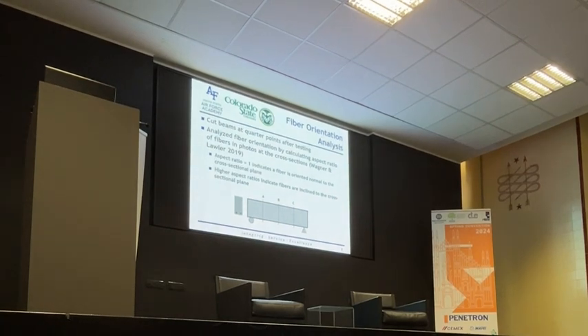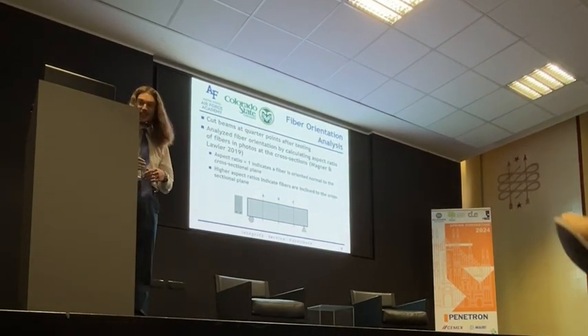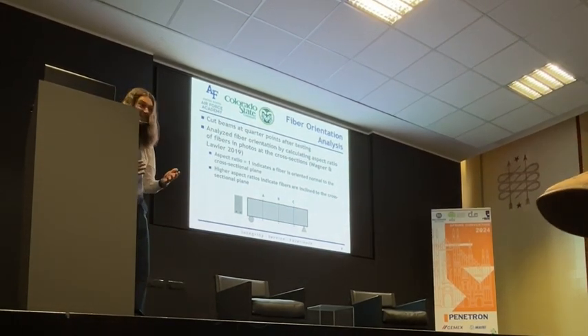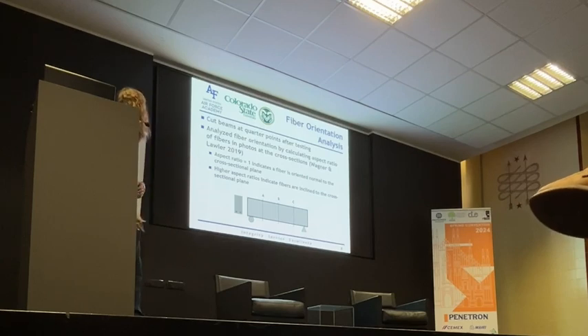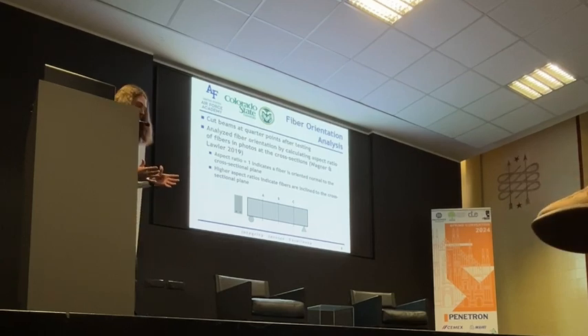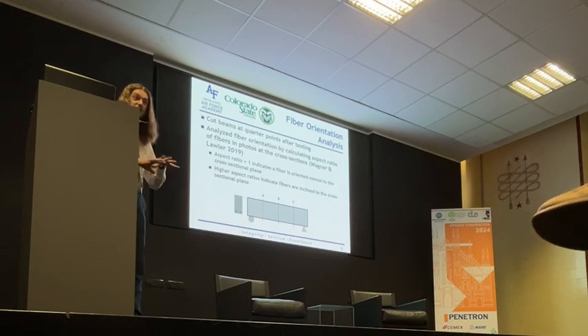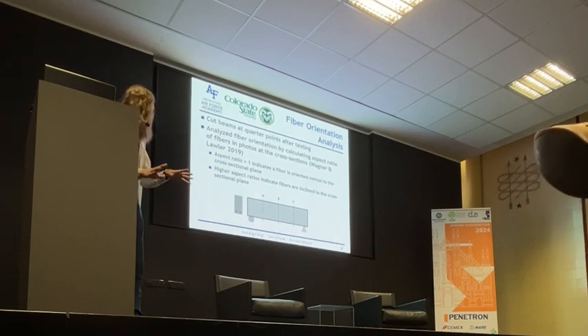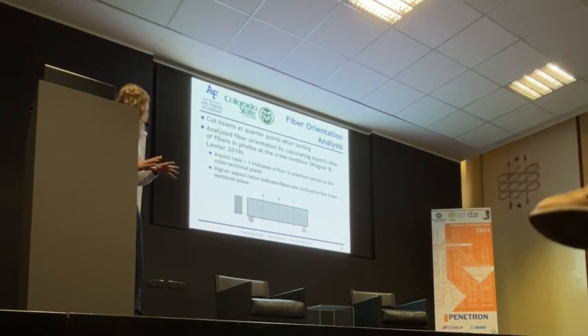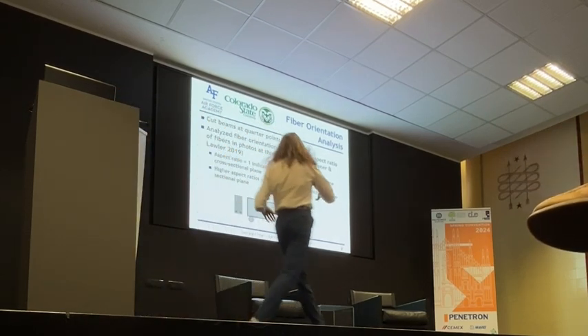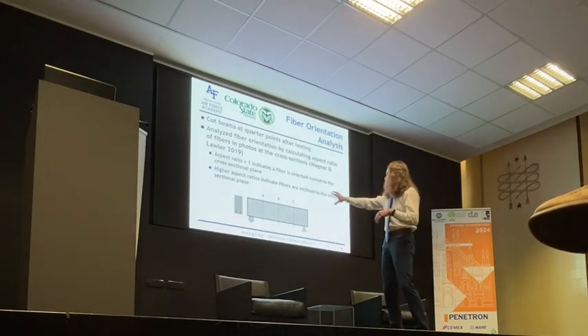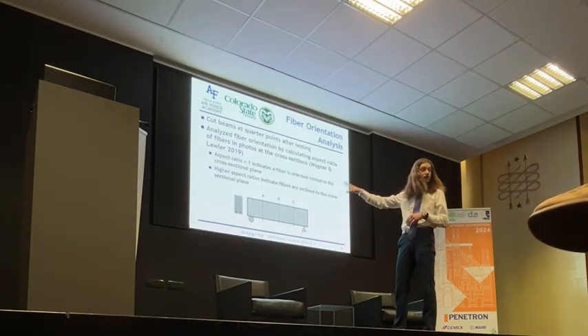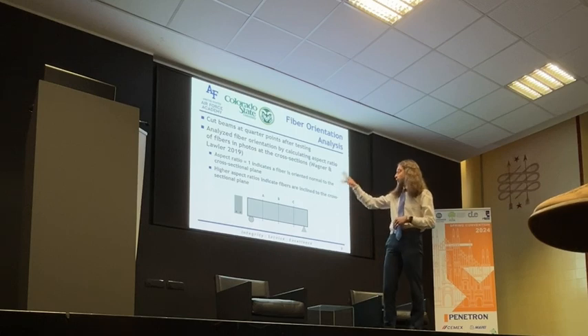All right, so we already had some great conversation about fiber orientation, and I'm going to add to that a little bit. So after we finished crushing our beams, we tested them until failure, and then we made 3 cuts. We divided each specimen into even quarters. So we're looking at this cross section. For reference, this longer portion is about 77 centimeters. This cross section is about 10 centimeters by 18 centimeters, right?